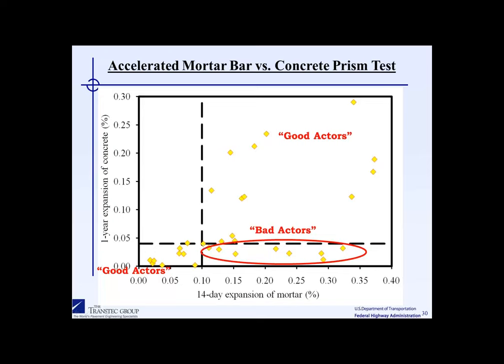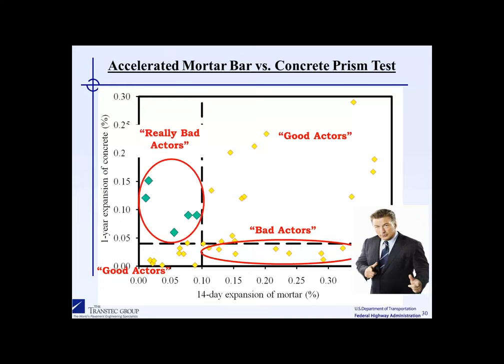Again, the reason that these bad actors exist, or the reason that the results are such, is because the high temperature is causing the aggregate to expand, even though it's essentially non-reactive. These would be considered the bad actors, the Alec Baldwins of the world. And this has been known for a long time. And there's parts of the world where people know they can't use the accelerated mortar bar test at all because the results will give you false results, such as these bad actors.